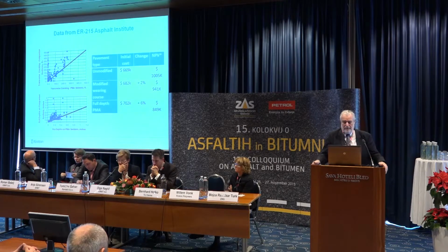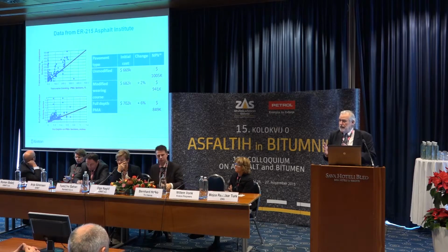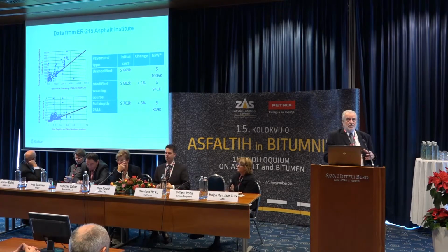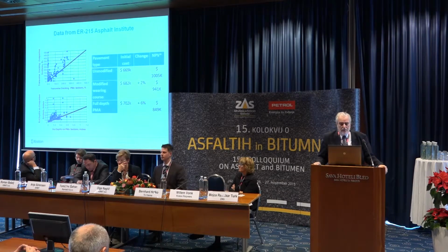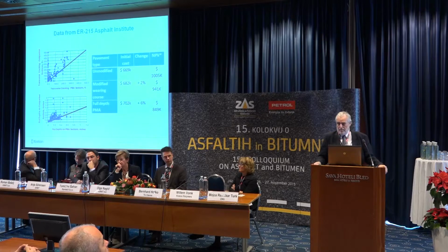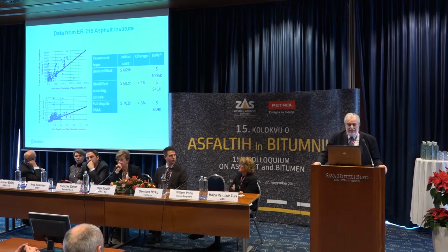Then they made some NPV calculations, and that is the standard story. PMA works better, it is more expensive, but does it really pay off? On the basis of these evaluations, they've made some model calculations, and as you can see, the initial costs are higher, but the NPV, the net present value of the polymer modified asphalt sections, was lower in a period of 20 years than of those not modified.